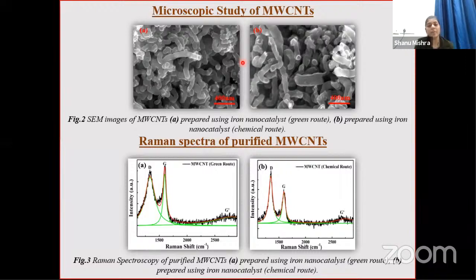After this, we took the Raman spectra of these CNTs, and we see the characteristic peaks of CNT in both cases. In figures 3A and 3B, you are seeing the Raman spectra of the CNTs, where the D band arises at 1350 inverse centimeters, which corresponds to the defects of the CNT, or you can say the defects of the graphene sheet. The G band, which comes around 1600 inverse centimeters, corresponds to the sp2 hybridized vibration of carbon atoms. The ID by IG ratio we have calculated by Lorentz fitting is around 0.9 for the green route synthesized MWCNT, and around 1.5 for the chemical route.